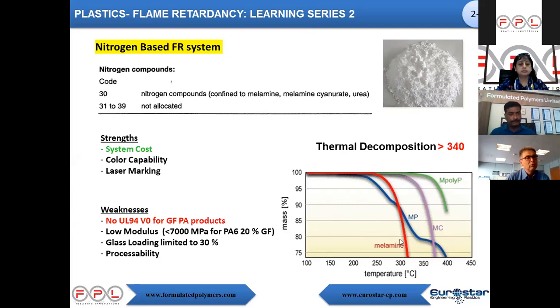Be careful, don't use melamine, because melamine is less stable and is water soluble. But this one is stable up to, let's say, 320 degrees C, so it can really be used in polyamide or in other polymers. It's really a chemical product from the chemical industry. The weakness of this product, as we'll see on the next page, is that it is a dripping system. So it works very well for UL94 V0 only for non-reinforced products,